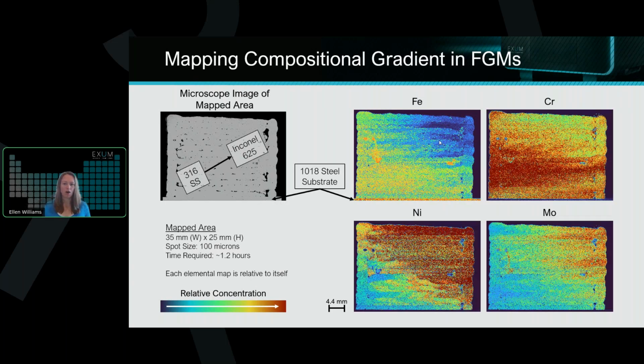So then we can look at all of the other elements of interest that we measured here. So chromium, for example, is relatively higher in the 316 and then transitions to relatively lower in the 625, but there's still quite a bit of chromium in the Inconel 625 as well. So we see high levels of chromium up in the top right of the analysis. Of course, nickel, we see the opposite trend as we do with iron, because nickel is the primary constituent of the Inconel 625. And then we see molybdenum mirroring the nickel pattern as well, since it is more present in the Inconel than in the 316.